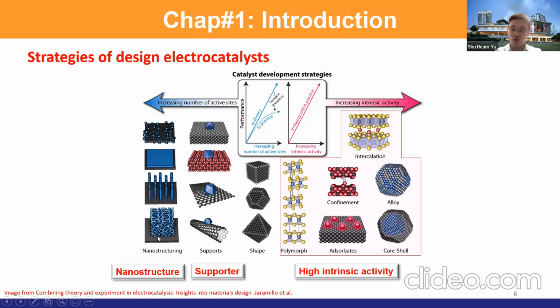We make the material smaller and smaller, or we can use a conductive electrical supporter, for example carbon nanotube, so that the catalyst can be well dispersed on the supporter. Or we can do some shape controlling to expose more active sites to the electrolyte. Certain shapes, certain crystals will have more active sites, so that it can be exploited for the HER reaction.